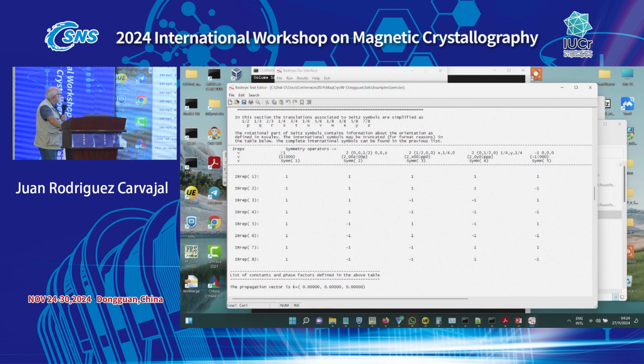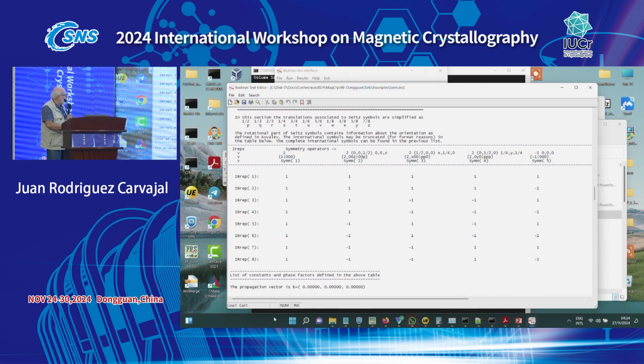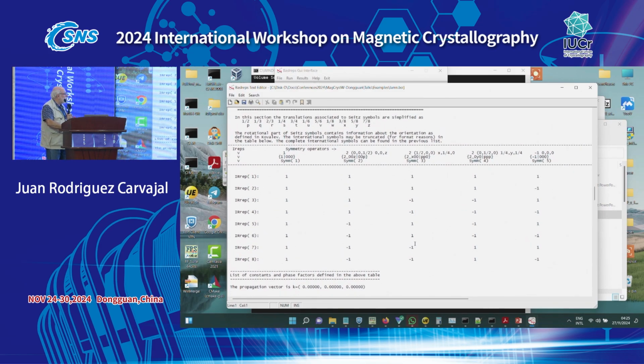You see here each symmetry element, here you have a sort of set notation, the elements like that, and you see all the characters. Because we have representations of dimension 1, they coincide with the characters. Another important thing is that there is a rule, a correspondence with magnetic space groups very easily here, of type 3 in that particular case, because k equals 0.